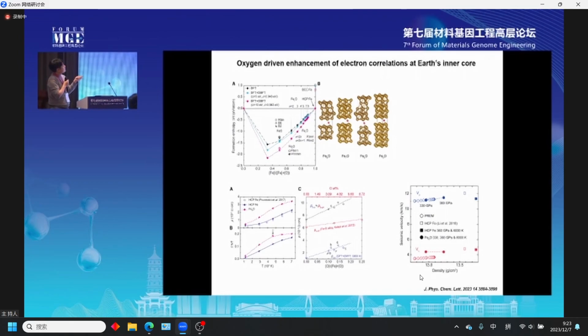But this is a DFT plus DMFT structural prediction result. It is interesting because with pure DFT structural prediction, the experimentally found structure, the black symbol, cannot be stable, cannot be the ground state. This is at high pressure, where we think the correlation effect can be much reduced, so standard DFT might work, but it does not. Even at very high pressure we need to include some correlation effect in this iron oxide system. If you correct by applying the DMFT result, the experimentally found structure can be stabilized energetically. So many-body effects are still important for describing high pressure materials, especially transition metal oxide systems. Other information is too detailed, so let me skip it.